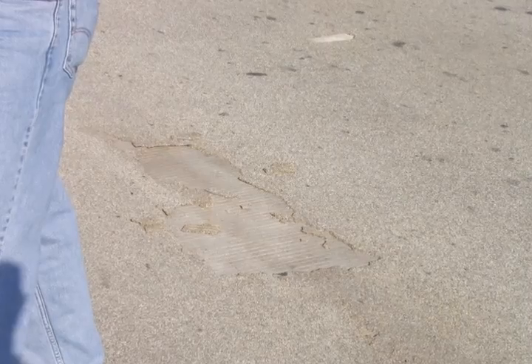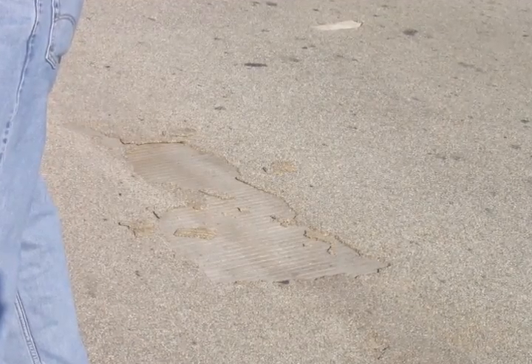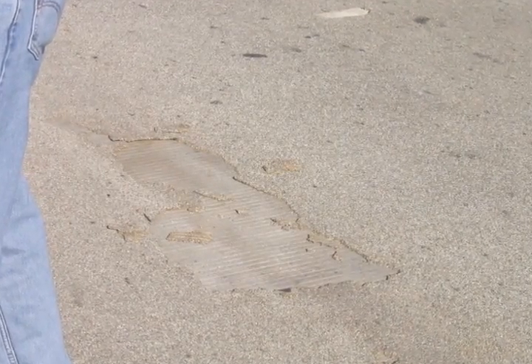The third and final type of protection I'd like to share with you is the use of surface treatments on bridge decks. You're looking in the center at the original concrete surface. What's been placed on it is an epoxy product, which is placed in a liquid form, and then afterwards, aggregates or small rocks are broadcast into the epoxy to produce a very highly skid-resistant surface that, when placed properly, will provide protection against chlorides and water. That is, it will be impermeable to the ingress of water or chlorides. In this case, no doubt the surface was not prepared properly, and debonding of that layer occurred. I'd like to show you a video now documenting the application of this kind of product on the roadway. The video was prepared by two of my students, Tyler Nelson and Reuben Collins.